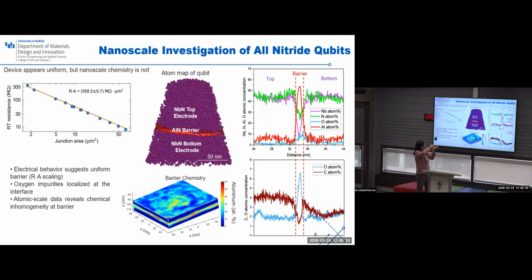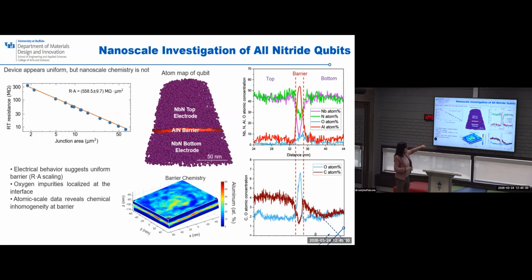Now this is three-dimensional. If we extract the barrier and look here, like you are cutting a plate and looking at it, what you are seeing here is the barrier chemistry. It is not homogeneous, because you can see the color map. The color map is showing the composition variability, and that shows that it's not homogeneous. If we see further the composition profile from electrode to barrier to electrode, we can see that the barrier layer is nice, but we see a lot of oxygen atoms. This is the killer. Oxygen atoms, generally when they are in the device, most of the time kill the device performance. It's not good, okay? So something is going on with the chemistry that we understand. However, we are still not able to understand where that subgap current is coming from.